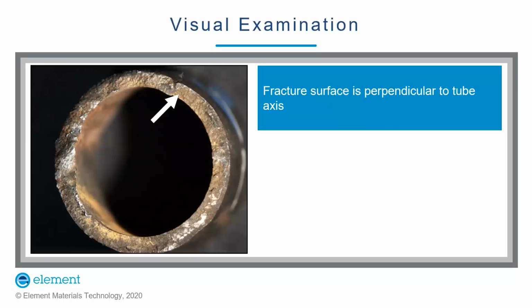Well, the first step was to do the visual examination of the tube surfaces of the failed tube, mainly a detailed observation of the failed tube, ID, OD, as well as the fracture surface, using a stereo microscope. As seen from the micrograph of the fracture surface, it appears that the fracture surface is flat and perpendicular to the axis of the tube.